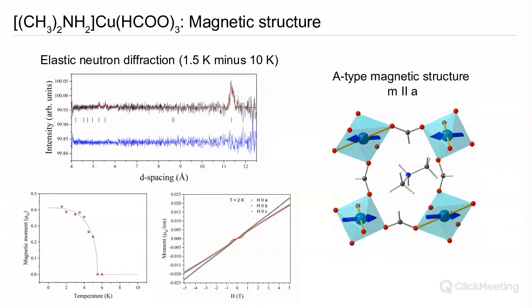We used neutron powder diffraction to then explore the magnetic structure further. Here I've plotted the data measured at 1.5K with the 10K data, the paramagnetic data, subtracted away, and we see these magnetic Bragg peaks. We can fit these magnetic Bragg peaks, and what we find is antiferromagnetically aligned spins along the C-axis, which are then ferromagnetically aligned in the AB plane, so a so-called A-type magnetic structure. So it seems that formate is mediating both antiferromagnetic exchange and ferromagnetic exchange in this material.